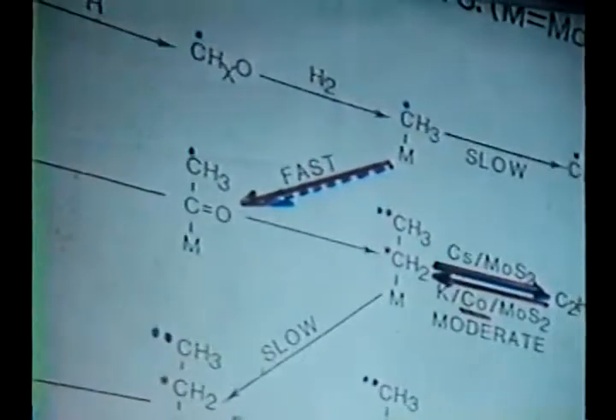But the major effect of cobalt is really here, to make this reaction, this first insertion, very fast. And that is what maximizes the product composition in ethanol. Even with cobalt, this second step here is slow. And that is further indication that after ethanol you have bottlenecks and the synthesis proceeds relatively slowly. This is all consistent with what is known in organometallic chemistry about CO insertion reactions. CO insertion into an alkyl metal bond, a methyl metal bond, is faster than into an ethyl metal bond, and so forth. So this looks like organometallic chemistry, although it is realized on a system that does not look like traditional organometallic catalysts.